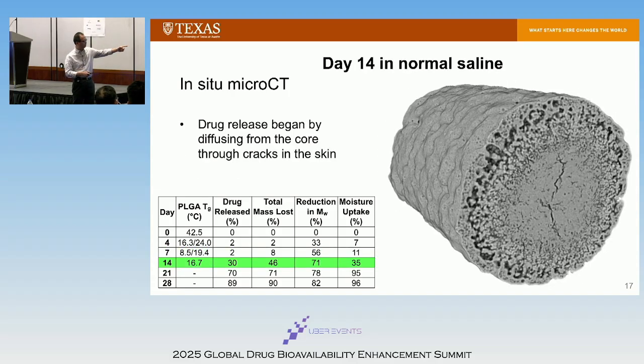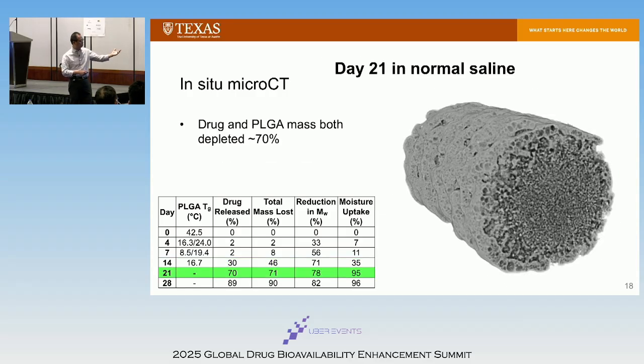14 days, that's where drugs start releasing. Look at 21 days. You see the difference in the skin and the core. Because in the core, there's an acidic environment. On the skin, you get buffered, even though we're on the normal saline. We run the dissolution in the normal saline, the inside pH is about 4, 5-ish.